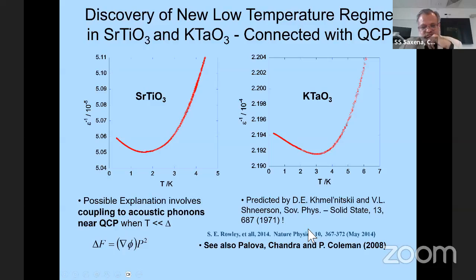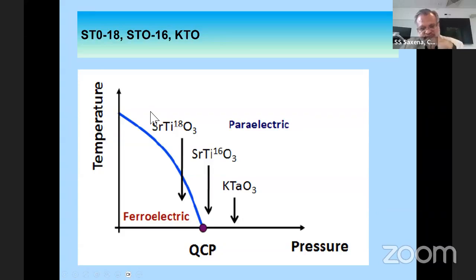But also it was done in our collaboration with us in 2008 when theoretically we looked at it, and we also found something similar in potassium tantalate. So it's not some artifact of the material or even of the cryostat. Now of course, it's been measured quite comprehensively. But let's go back to strontium titanate for a second and study it.